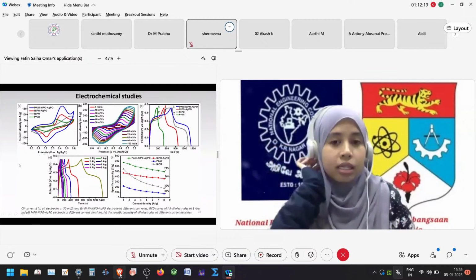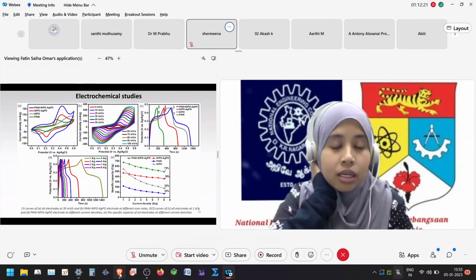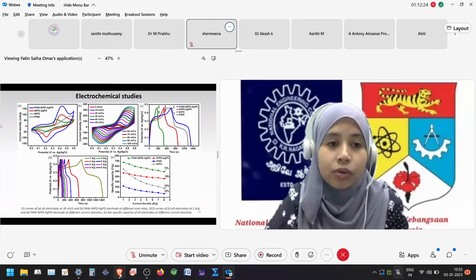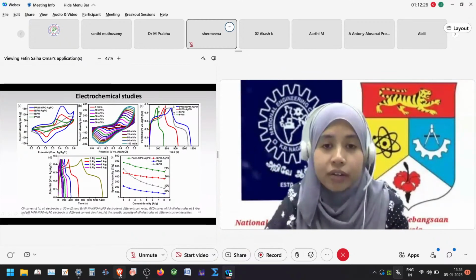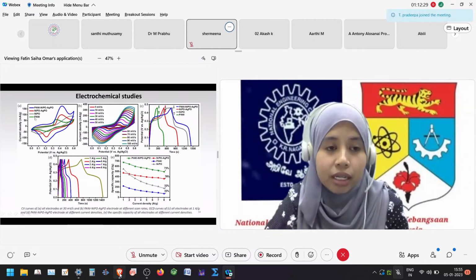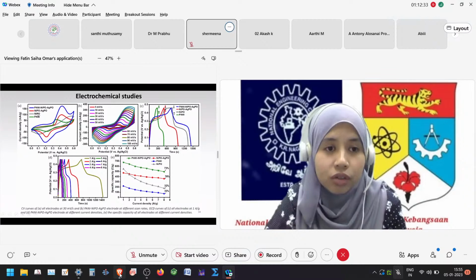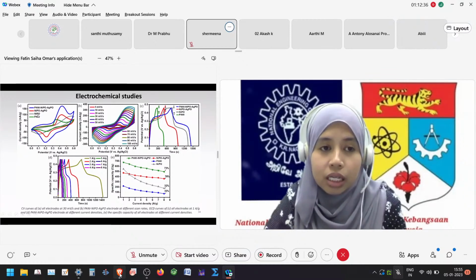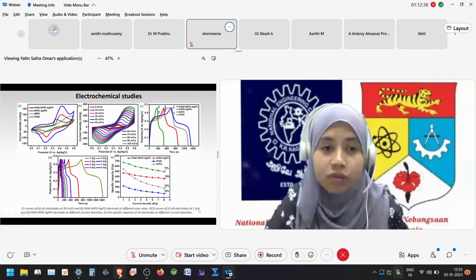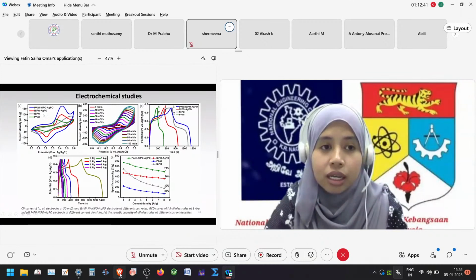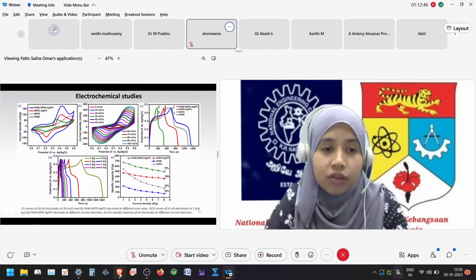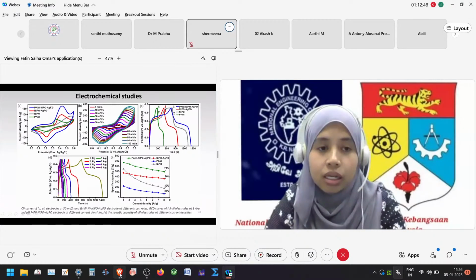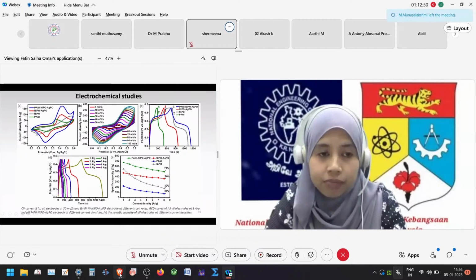Okay, this is an example of the electrochemical studies. For figure A, in this work, we prepared 4 different materials. First is polyaniline, second is nickel phosphate, which is amorphous nickel phosphate, and third is nickel phosphate composited with silver phosphate, and fourth is the composite of polyaniline, amorphous nickel phosphate, and crystalline silver phosphate. So in this CV, we can look at the area under the curve.